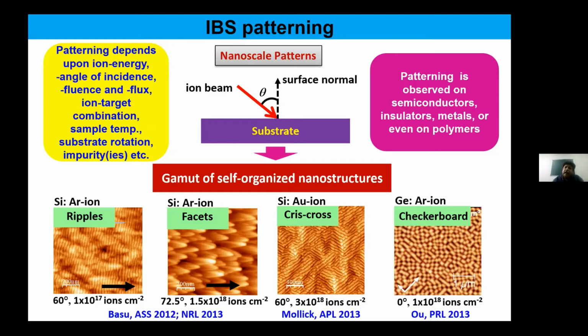And it's important to know that patterning, that is this self-organized pattern formation due to energetic ion bombardment, is observed on semiconductors, insulators, metals, or even on polymers. Almost all kinds of materials, we can generate such patterns. The only thing is that we have to keep in mind several experimental parameters. These parameters, which are listed here, may give rise to very different combinations of patterns which may evolve. So depending on all these things, one can form a gamut of self-organized nanostructures on several material surfaces.